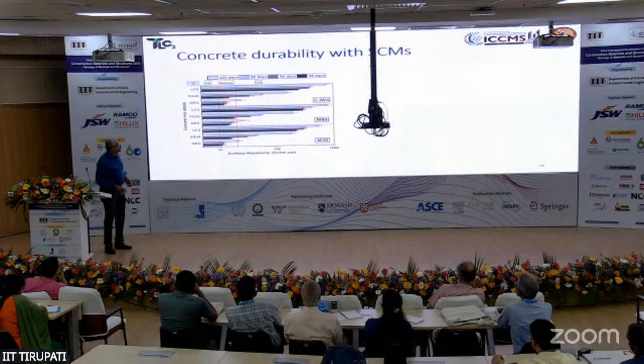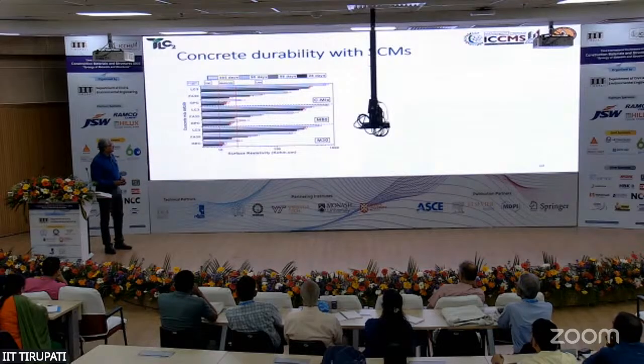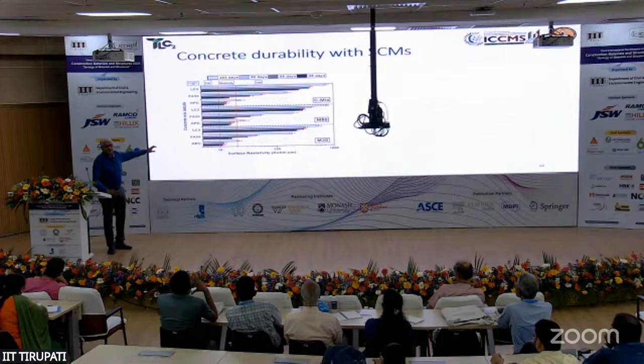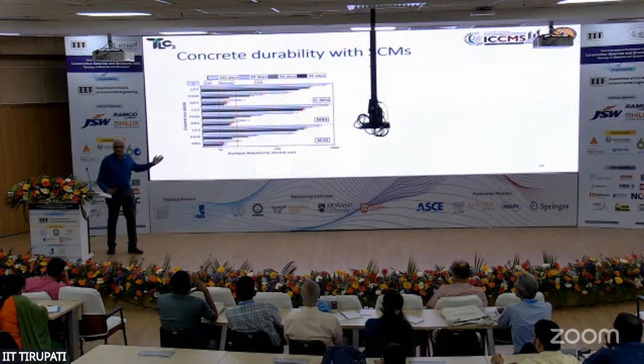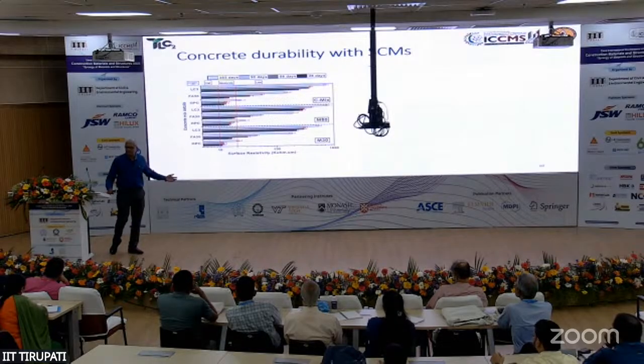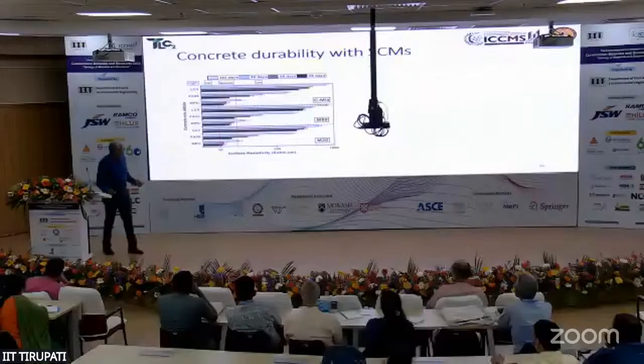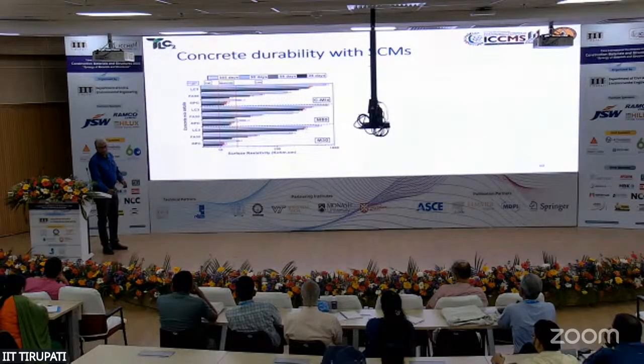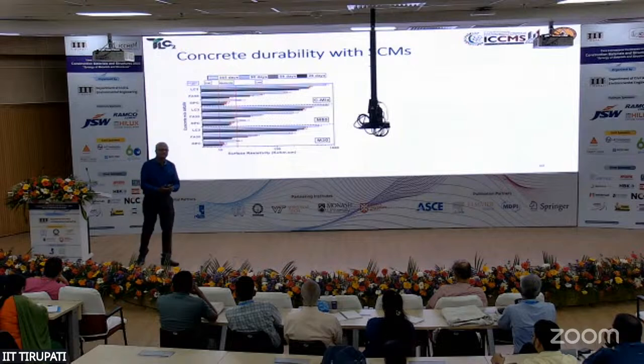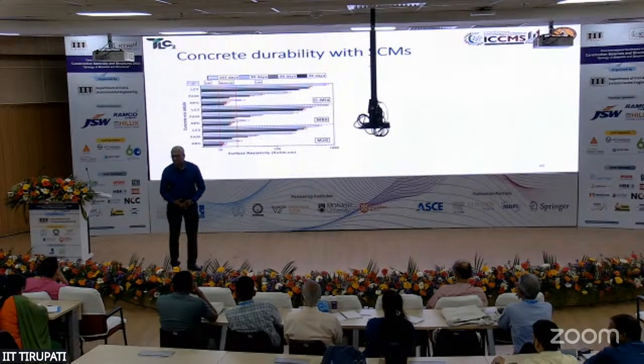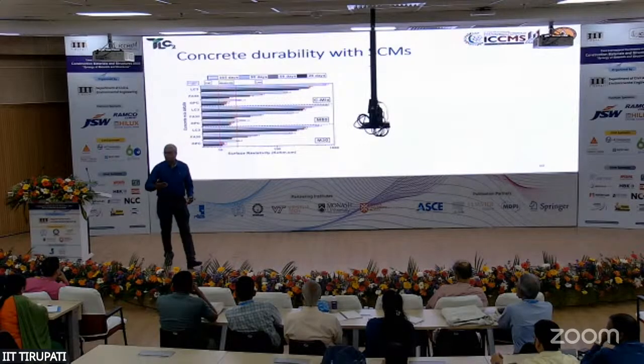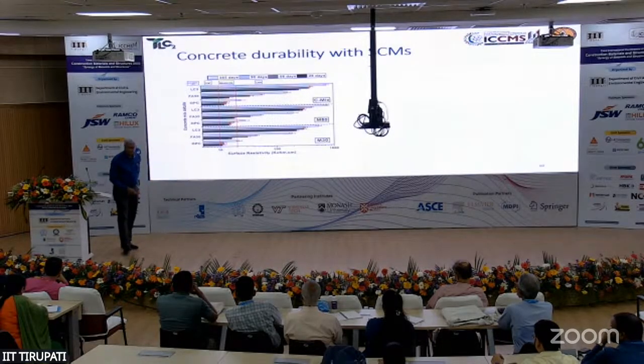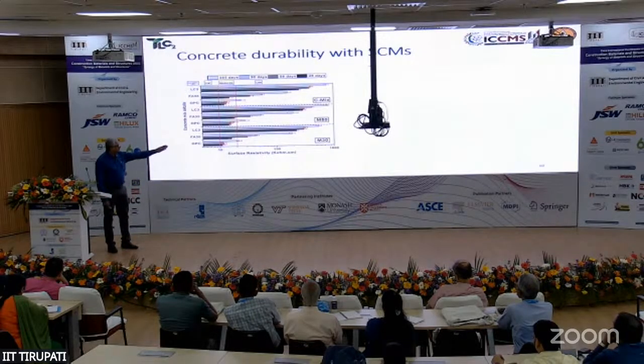Now, what about concrete durability with supplementary materials? This is part of some research work that we had done, comparing the performance of concrete with ordinary Portland cement to concrete with 30% fly ash replacing cement, and then limestone calcined clay cement. So this was from an industrial production of limestone calcined clay cement that was undertaken by one of our cement companies. And you can clearly see here in terms of your resistivity. So resistivity is a durability parameter that directly links to how disconnected the pore systems are. So the higher the resistivity, the better the durability, right? So here you see, even for a concrete which is of a residential grade, like 30 megapascals concrete, you have resistivities of LC3 which are an order of magnitude higher than that of OPC.